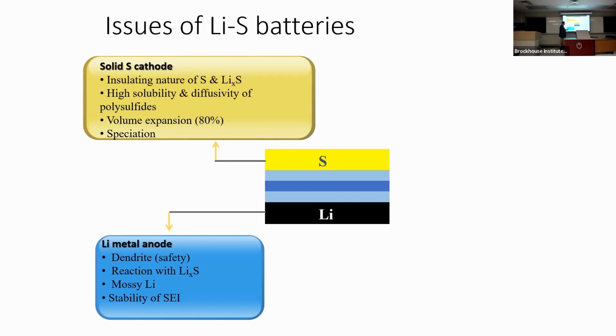Okay, but however, if it doesn't form dendrite, it forms various kinds of mossy lithium. It sort of leaves spaces. So therefore, that lithium is never in contact properly with the electrolyte. And there is what is known as the solid electrolyte interface. That's key in a battery, because that electrolyte interface must be ionically conducting, but be stable and not consume so much of the electrolyte that it keeps growing. After a while, it cannot have much power left in it because it's a huge resistance. So that must be stable. It's a dynamic process. It's not built once and stays like that.